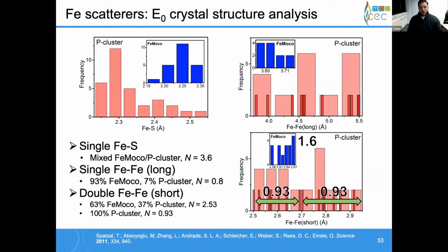And lastly, for the short iron-iron distances, for FeMoco, these are pretty tightly conserved within a range of about 0.1 angstroms, and the P cluster is much more spread apart, but it's not so spread apart and not so skewed as in the iron-sulfur distances. And so here we're actually going to split these into two shells. One that's going to involve FeMoco and the shorter P cluster iron-iron distances, and one that has the slightly longer P cluster only iron-iron distances. So we have a single iron-sulfur, an iron-iron long, and two short iron-iron scattering pathways we're going to invoke here.